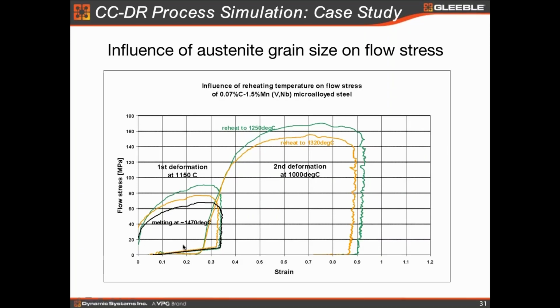And here is the flow stress curve that we measured at three different peak temperatures. What we can see is, of course, you can do multiple hits, about 5, 7, no problem, because the Gleeble also has the feature of hydraulic control. You can control the strain rate and temperature intervals very well. And here, what we see is, the finer the grain, the larger the flow stress you observe. Like you see the low flow stress at the 1470 melt zone. We deform at the same temperature. The only difference is the grain size. So the finer the grain size, the larger the flow stress you get. The same for the 1000 C deformation, heated at 1250 and 1320.